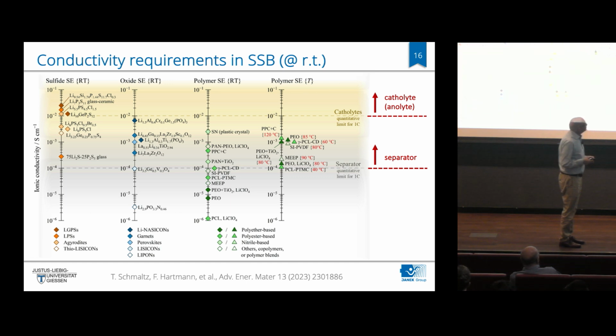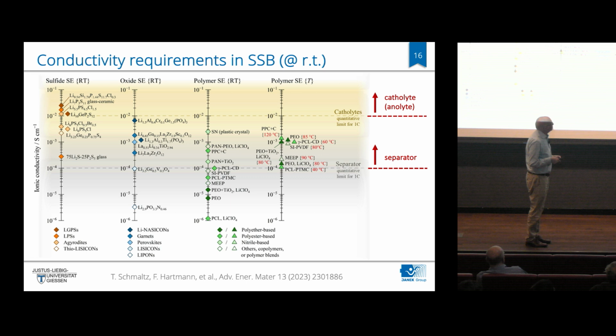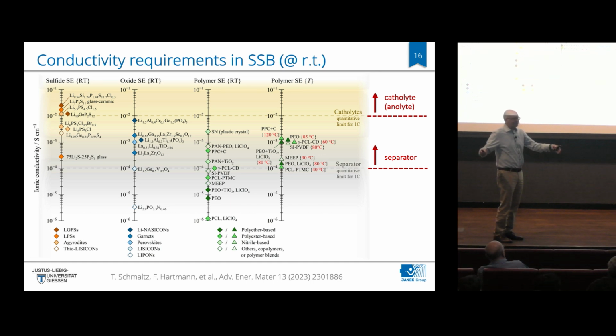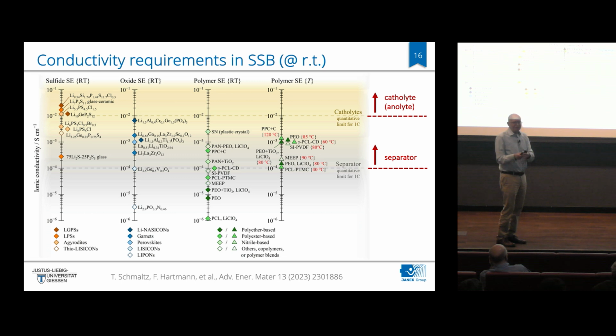And there's, I would say, quite a number of electrolytes that have higher conductivities: sulfides, oxides, polymers. So I think there's a good range of materials that can be used as a separator. But the critical point is the electrolyte in the electrodes, particularly in the cathode. It has to be thick to store enough charge. And if it's thick, you need a top electrolyte with a very high conductivity to have low enough resistance to transport the ions across the electrolyte.